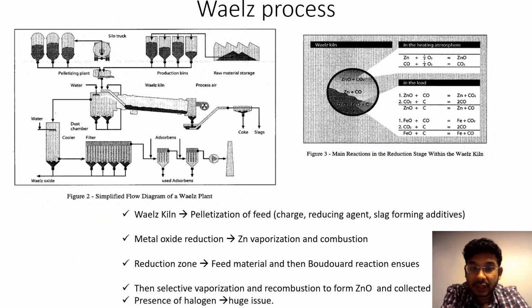Okay, let's get into the nitty-gritties of the Waelz process. It happens in a Waelz kiln, and the first step is pelletization of the feed. So you have input of your charge, and then the reducing agent, which is of course coke, and then you have all these slag forming additives. So the first thing that happens is in the reduction zone. Okay, so you have zinc oxide or all the components that are present in the charge in the waste getting into contact through the Boudouard reaction. So you have the carbon dioxide that is in the chamber, right? And then the Boudouard reaction is basically carbon dioxide combining with carbon to produce carbon monoxide.